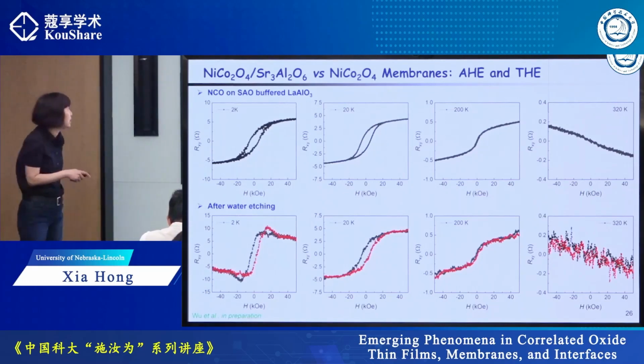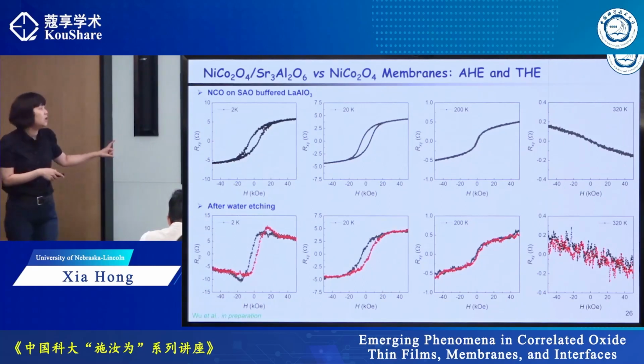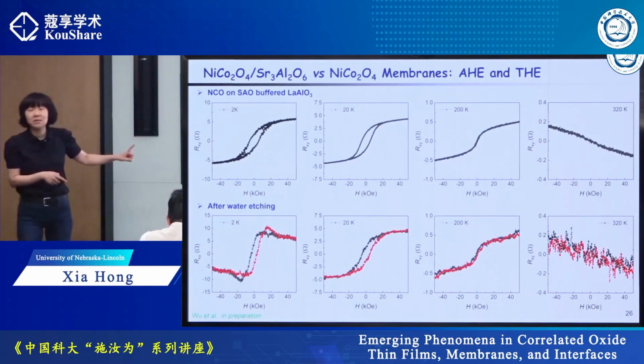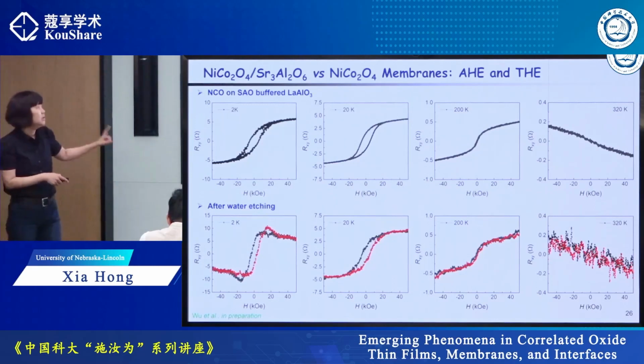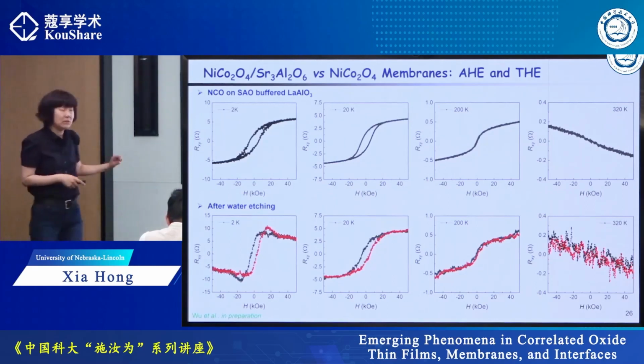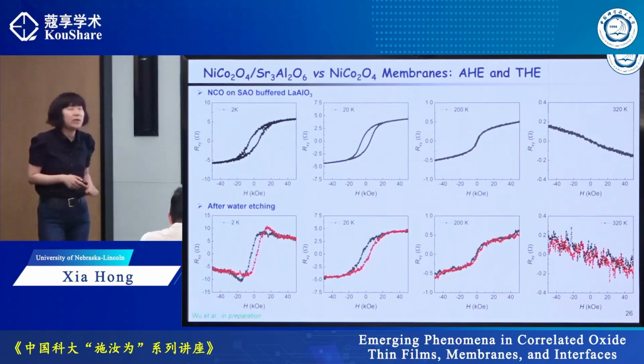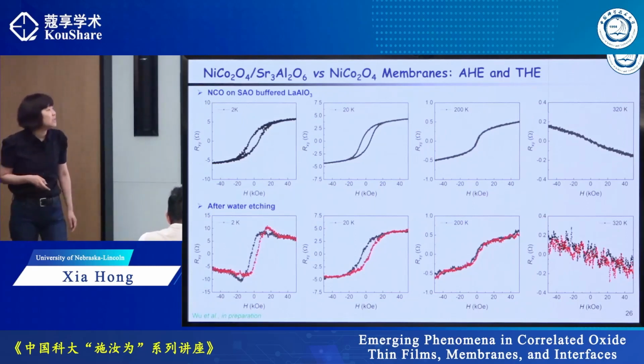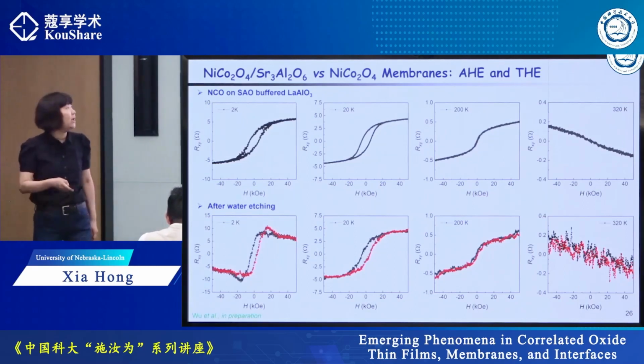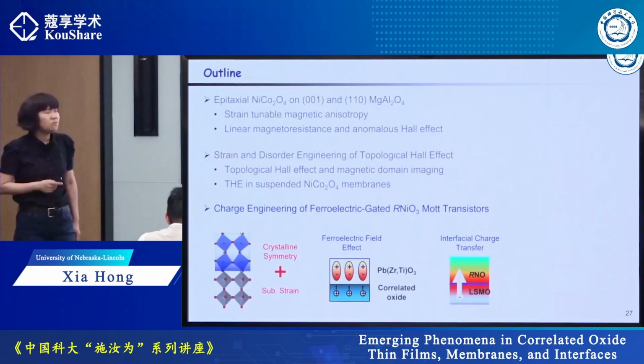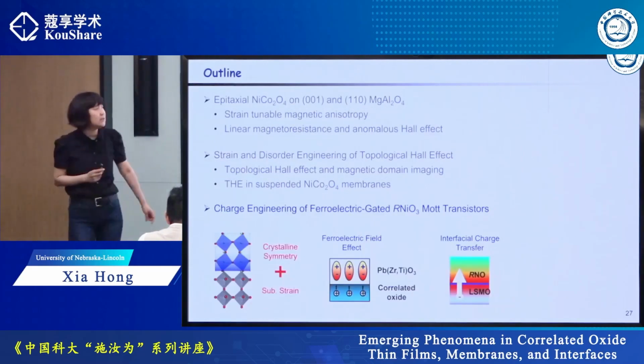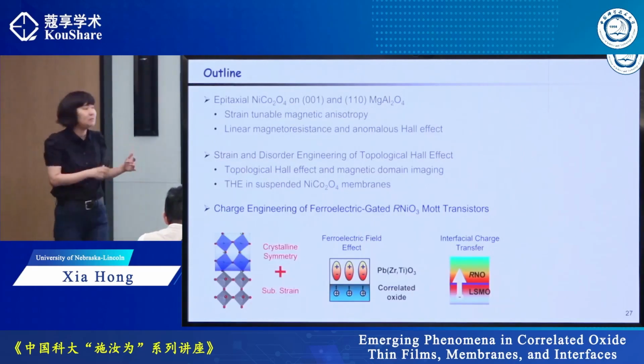But surprisingly, you actually see topological Hall effect at a low temperature. The origin of this topological Hall effect is not clear at this point. It requires an MFM study on this sample, which is currently going on. So this is the first material system I'd like to discuss. It's related to the magnetic properties.